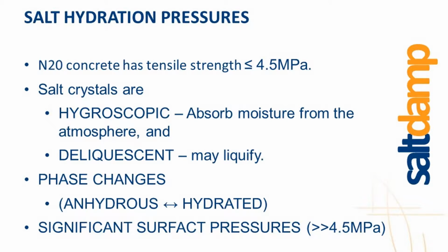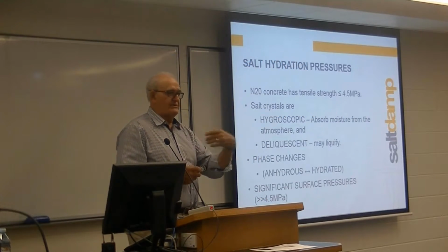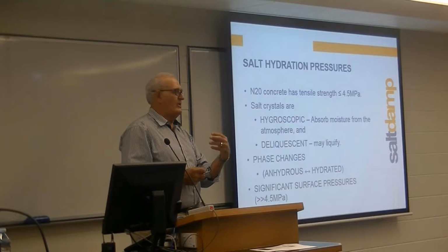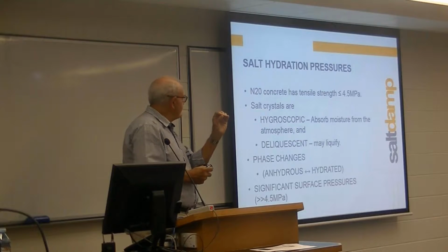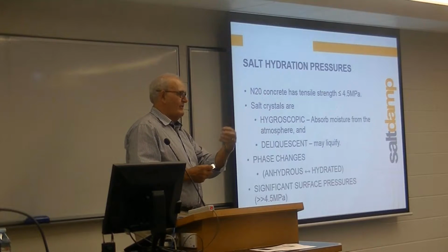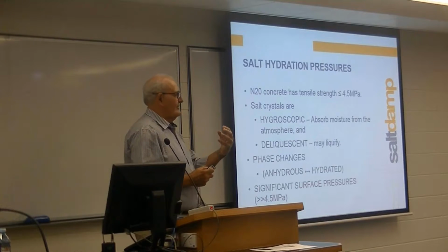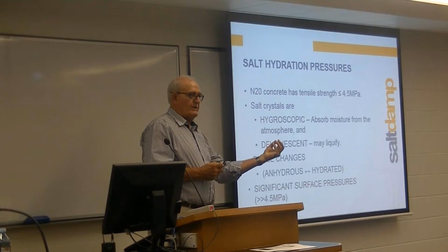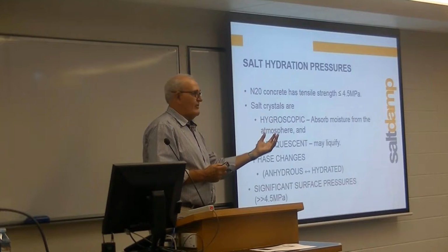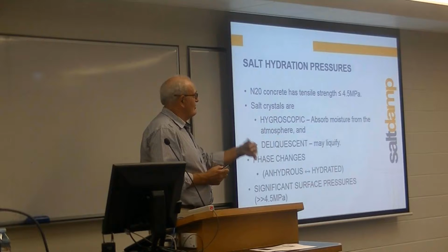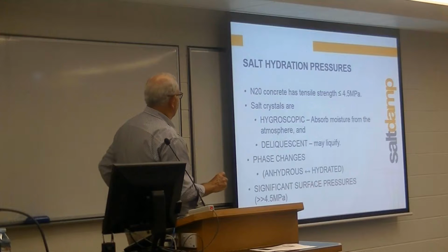As I said, when the saline solution gets to this surface of evaporation, the water leaves the solution as water vapour, but it leaves behind the solute, namely the salts. They sit in these little near surface pore spaces, and they will change their volume, that is the size of the salts will increase and decrease relative to them being able to absorb water of hydration molecules from the atmosphere or from rainfall, wetting and drying cycles, sprinklers splashing against walls, raining 1 minute, sunny the next, like this sort of weather we're having now is very prone to this sort of thing.